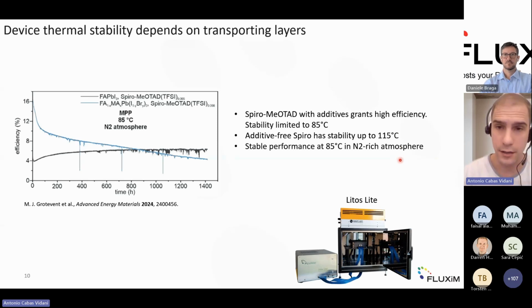In this case, again, he didn't want any contribution from the environment in order to fully focus on the stability of the transporting layer, and he also needed to measure multiple samples in parallel. So this is why he went for a larger sun simulator, connected again to LITOS Lite, and the performance was tested at 85 degrees. And you see here the overall efficiency is rather low, but it was rather stable over up to almost 1,500 hours. So this is an indication that the hole transporting layer needs quite some attention.